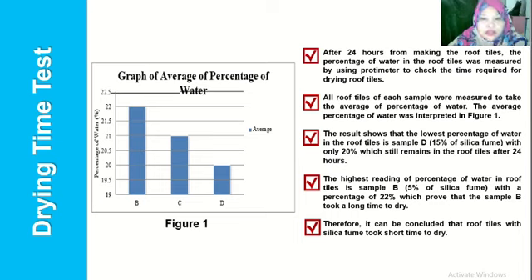The result shows that the lowest percentage of water in the roof tiles is in sample D, which has 15% silica fume, with only 20% remaining in the roof tiles after 24 hours. The highest reading of percentage of water is in sample B, which has 5% silica fume, with 22%, which proves that sample B took a long time to dry. Therefore, it can be concluded that roof tiles with silica fume took a shorter time to dry.